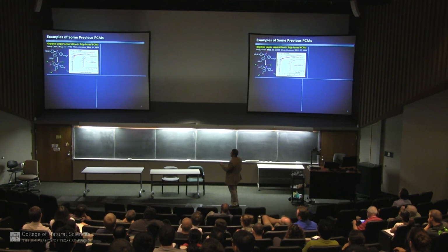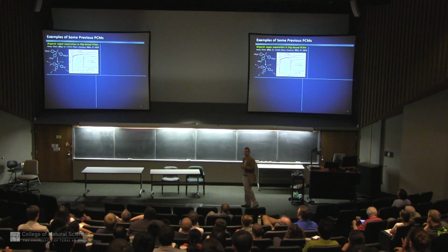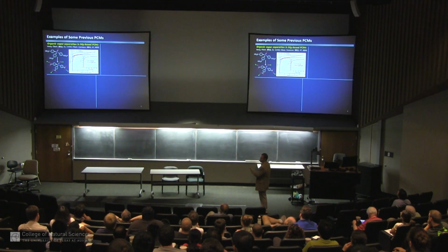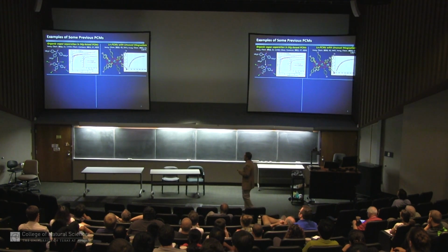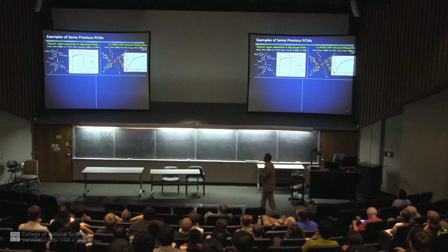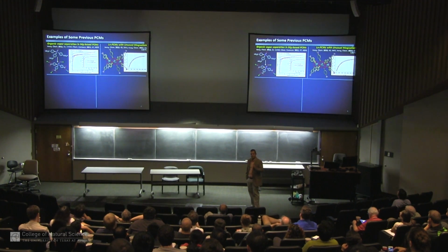We can take phosphine oxides, and these make very highly coupled materials because you can also couple through this PO group. And we've shown this material, for example, is useful for separation of alkanes that can't be easily separated by distillation. So we can do this by size, cyclohexane versus hexane. We do a lot of work with lanthanides, and one of the things that comes from this is unusual materials with metallic clusters that are interesting for their solid-state magnetism. I'm not talking about magnetism today, but this comes from my PhD, which was all magnetochemistry.